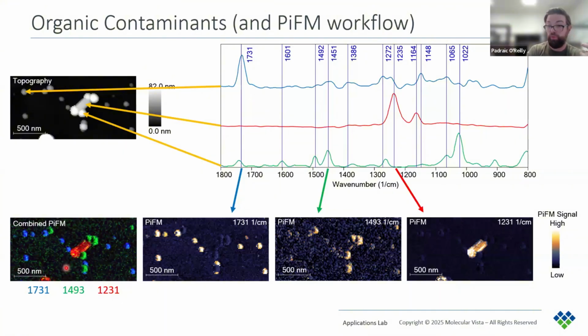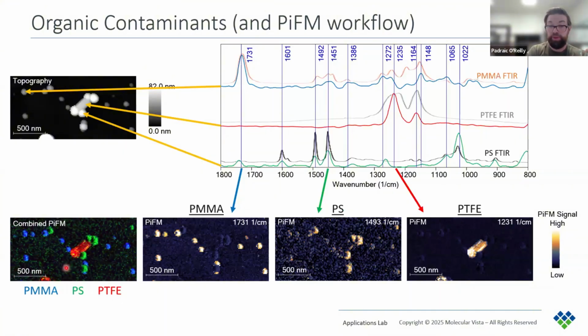And then finally, we can run these spectra in IR databases, and we can identify the contaminants as PMMA, PS, and PTFE. So this is just showing the general workflow of a PiFM experiment, but it also shows one of the strongest uses of PiFM, which is to identify nanoscale organic contamination.